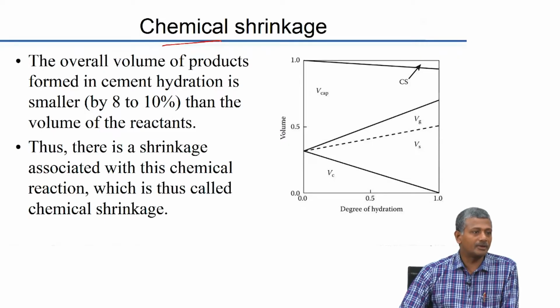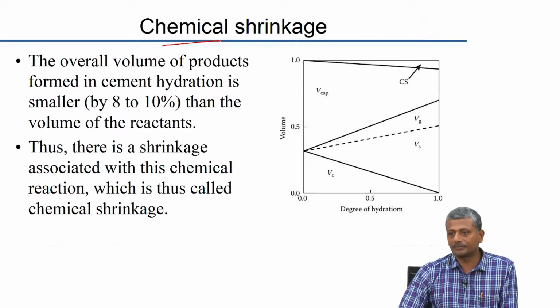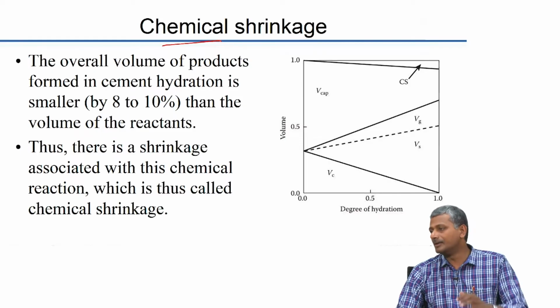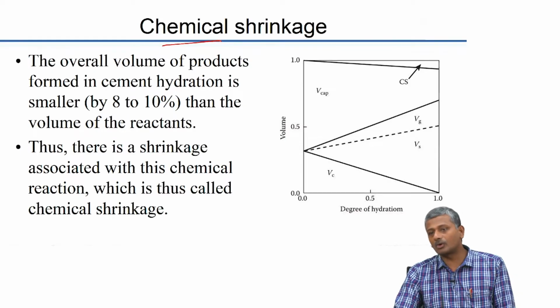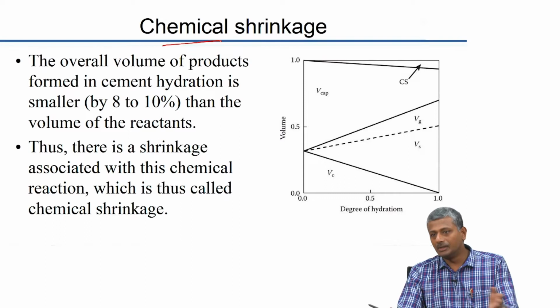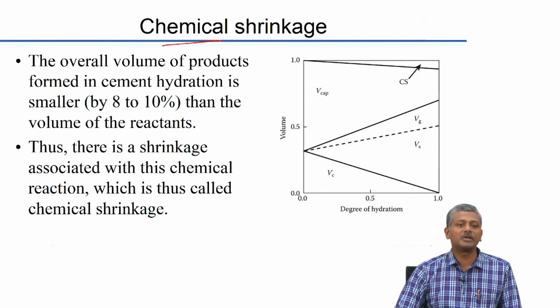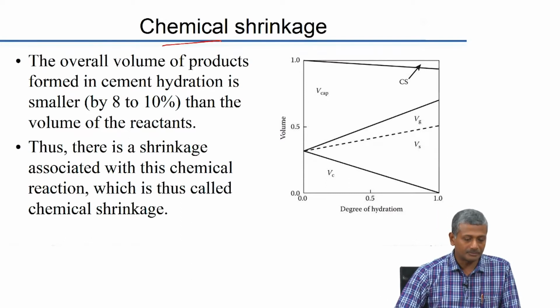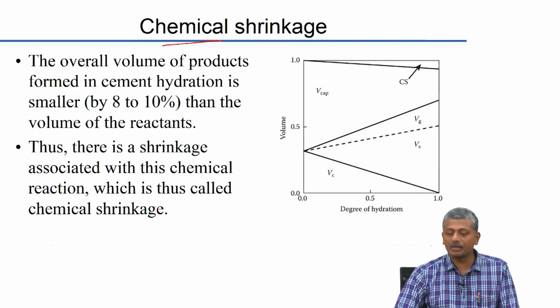Okay. So, the overall volume of the products that is forming in cement hydration is smaller by about 8 to 10% as compared to the volume of reactants, and that 8 to 10% approximately is 25.4% of bound water content. That is basically a theoretical value. The really experimentally observed values are between 8 to 10%. So, that is why it is called chemical shrinkage.